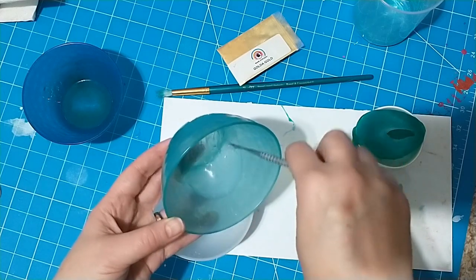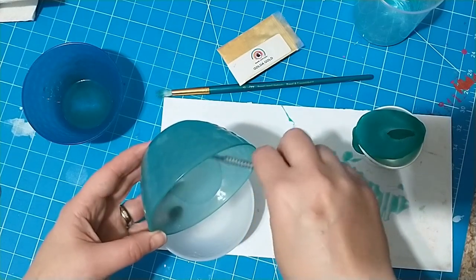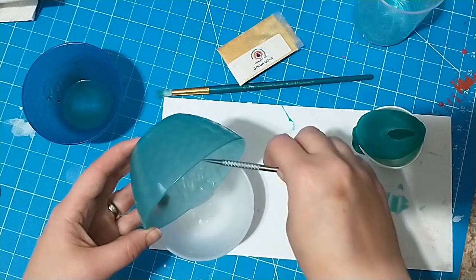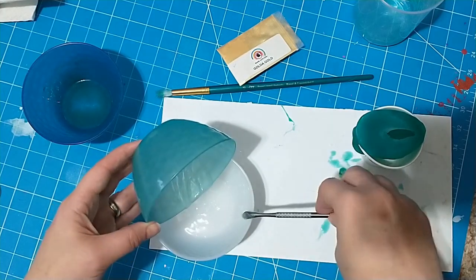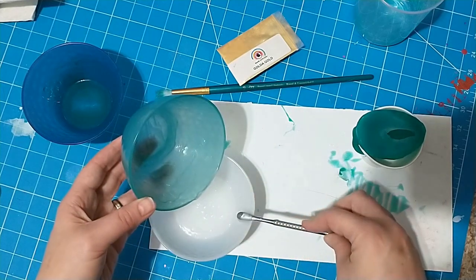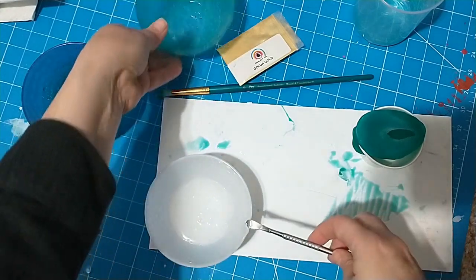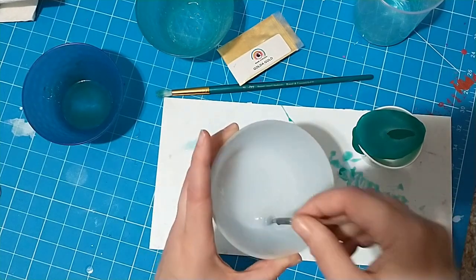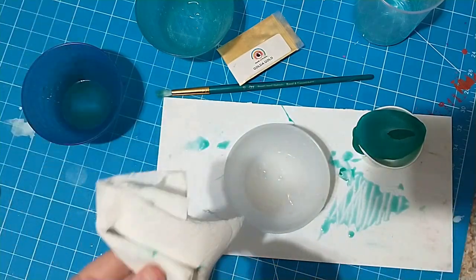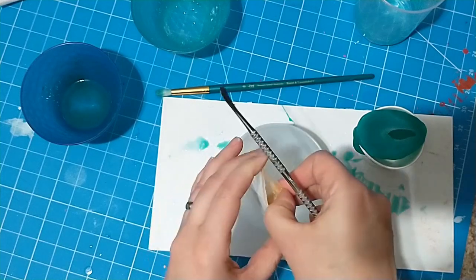So it's hard to film everything that happens here, because a lot of the time I like to vacuum the silicone. I have a vacuum chamber, you put it in, the pump pulls out the air, so then the vacuum pulls out all of the various gas bubbles that are dissolved in the silicone. And for long-term body uses, if you know what I mean, that is ideal, because without that there can be microscopic, tiny, invisible bubbles in your silicone, and those bubbles can harbor bacteria and become unclean after coming into contact with the human body. So, you know, you don't want that.